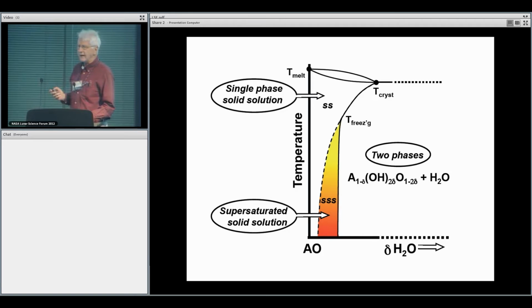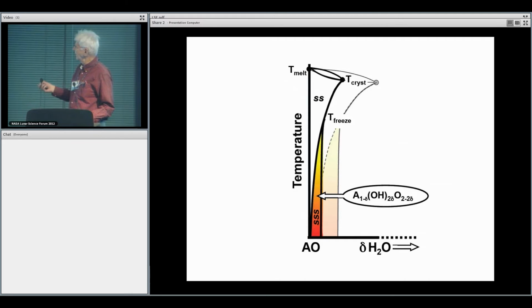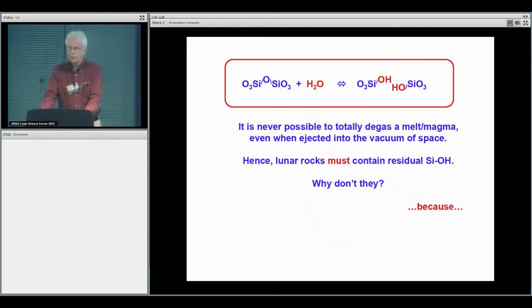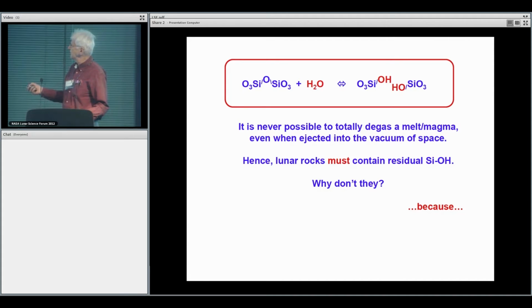And even if the degassing, in the next slide, is more pronounced, you may go a little bit further down this axis here, but you can never reach zero. So there will always be some residual OH present in these minerals. The next slide then shows the basic, very fundamental reaction. You take a tectosilicate, let's say a feldspar, you react it with water, and you break the Si-O bond, and you form an OH pair by breaking this bond. And this is not possible to degas. There must therefore be some residual.